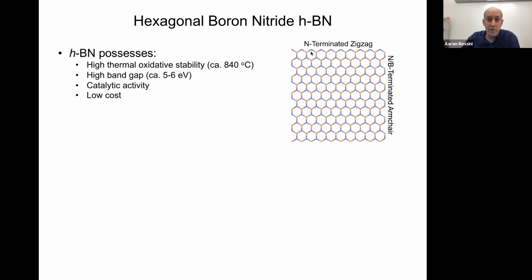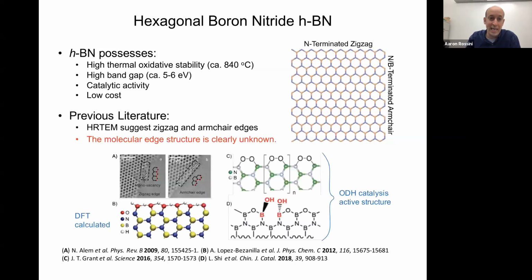So one of the fundamental questions that we came across when we were studying this material is that nobody really knows what the edge or termination of this material is. What is the molecular structure of the edges? And so if you start doing some digging in the literature, there's been some nice high resolution TEM studies where they've deposited single layers of boron nitride onto pristine polished metal surfaces. And you can pick out zigzag edges and armchair edges. So the zigzag would be this edge termination. This would be the armchair.